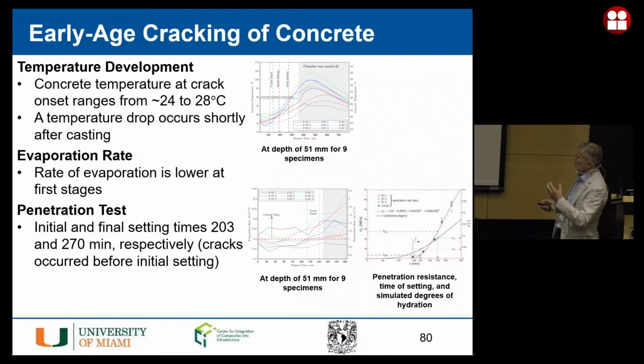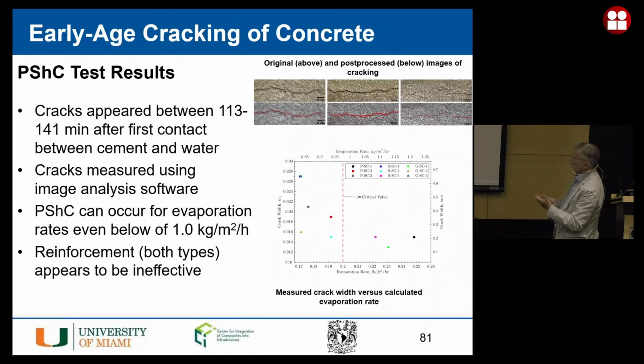So we have measured with a penetration test the setting time, and fundamentally what we're saying is that the shrinkage cracking, or the plastic shrinkage cracking, is a function of many things, but the contribution of the reinforcement is practically zero, because before the concrete sets, which takes approximately between 3 to 4 hours, the level of bond that you have is insignificant. So we monitor these cracks, we come up with different methodologies to look at them, and then we measure them. We have also imaging tools that allow us to see where they are. So I think it's exciting, but we are more on the material side.